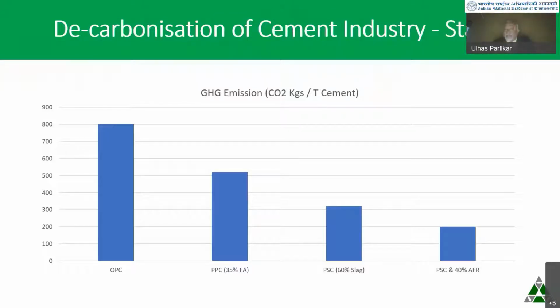If you look at decarbonization status, if you produce OPC, which is the conventional cement called ordinary Portland cement, the cement industry said that they want to reduce emissions. So they started looking at other options of utilizing waste material. When you put in fly ash, and if you are allowed 35% fly ash, you can reduce from 800 to something like 500 kgs per ton of cement. Instead of fly ash, if you use slag, which can be incorporated as per standard up to 60%, this gets reduced to something like 300 kg per ton of cement.